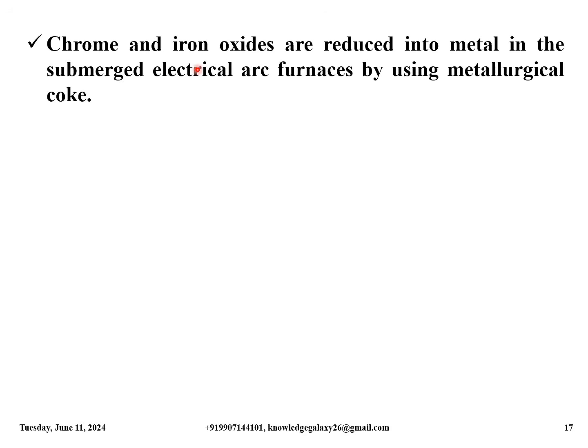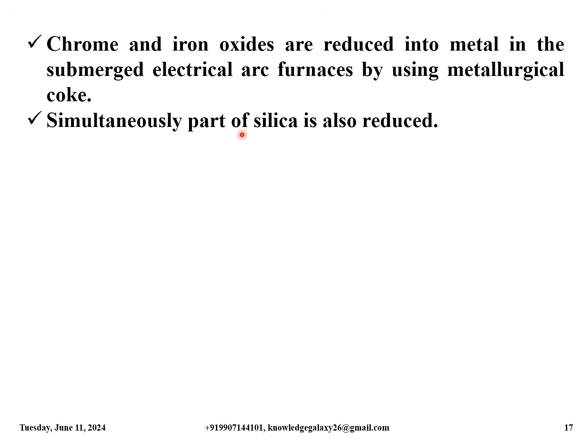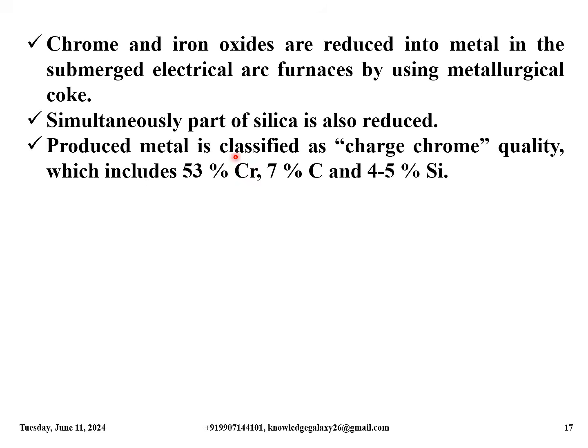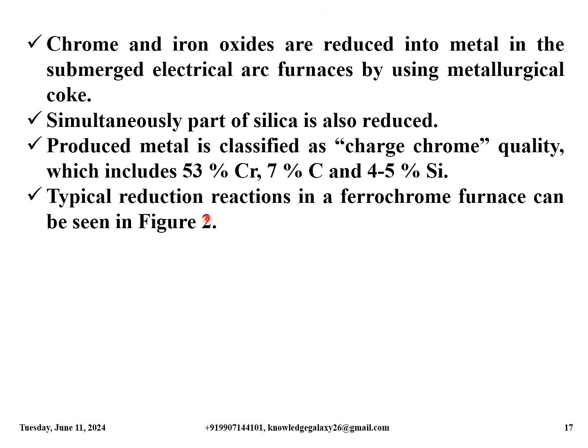Coming back to the presentation and continuing, chrome and iron oxides are reduced into metal in the submerged electric arc furnaces by using metallurgical coke. Simultaneously, part of the silica is also reduced. The produced metal is classified as charge chrome, the quality of which includes 53% chromium, 7% carbon and 4 to 5% silicon. Typical reduction reactions in a ferrochrome furnace can be seen in figure 2, which is given in the next slide.